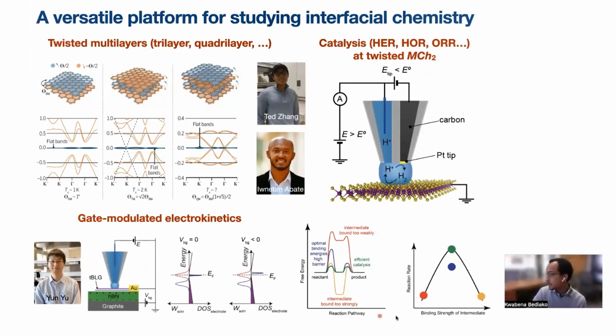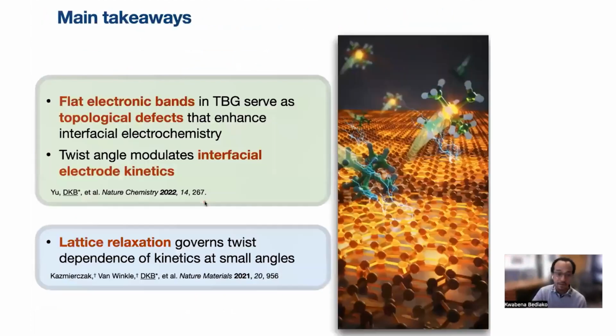Okay, so again, here are the main takeaways. I hope to have shown you how these Moiré superlattice-based flat bands can be used to modulate interfacial chemistry. So the twist angle itself becomes a descriptor of the interfacial kinetics, and the lattice relaxation that we've measured by 4D STEM helps us to understand the twist angle dependence.